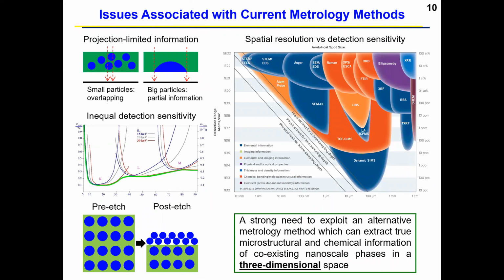Since cross-sectional TEM specimens are thin slabs of thickness less than 50 nanometers to be electron transparent, the technique only provides nanocomposite microstructure from a 2D perspective. Therefore, TEM has an intrinsic limitation in identifying how secondary crystalline and glass matrix phases are distributed in 3D space. Understanding such a spatial distribution of the phase is critical in understanding the optical performance of the composite media, as it is impossible to model the optical functionality of device performance without the spatial distribution and variation of such microstructure.